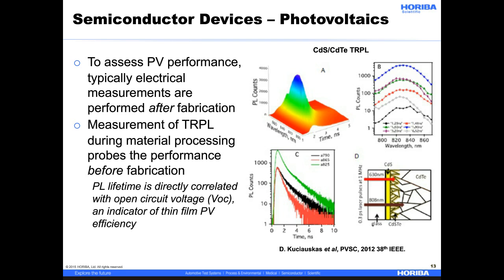By measuring the lifetimes at different PL wavelengths, the carrier dynamics of different spatial regions of the device can be probed. In addition, in this experiment, the authors of this study varied the excitation wavelength, thereby changing the absorption depth in the sample. Shorter wavelength excitation has a shallower absorption depth and can probe the cadmium sulfide-cadmium telluride interface, while longer wavelength excitation near the band gap is absorbed deeper in the sample, reaching the bulk cadmium telluride material.